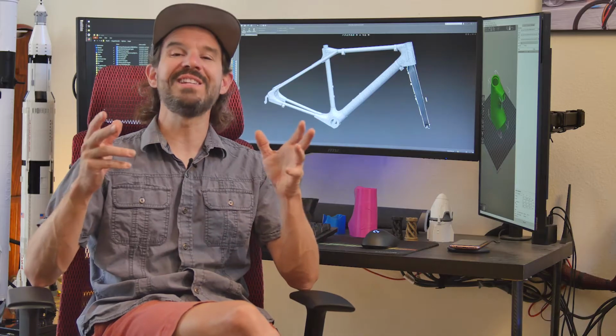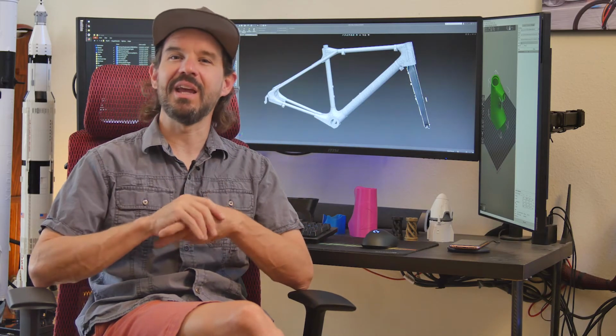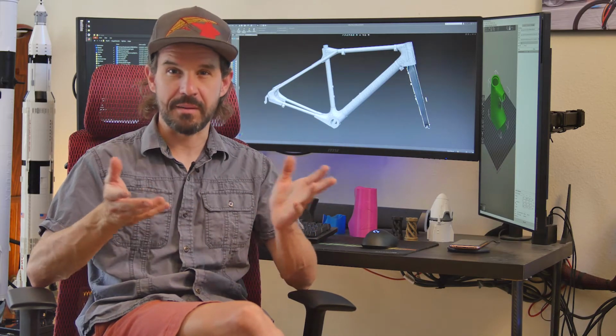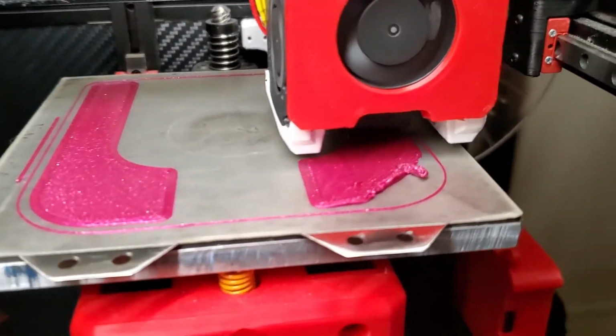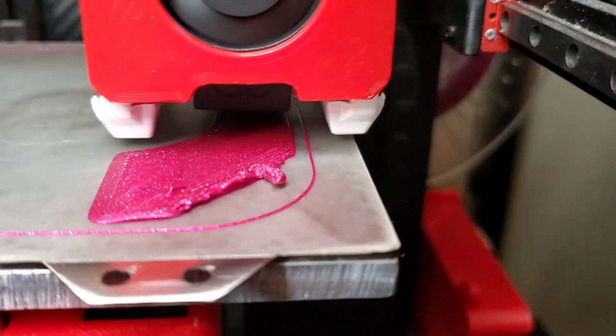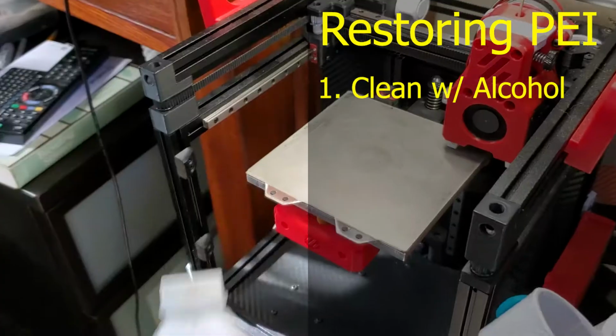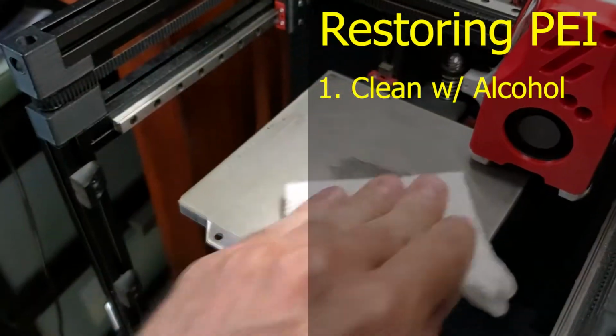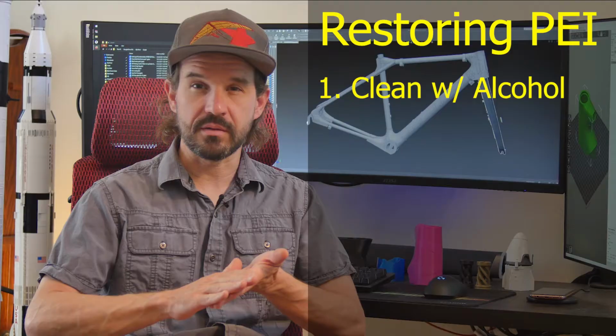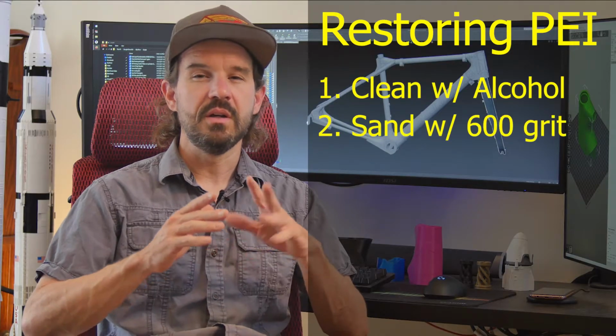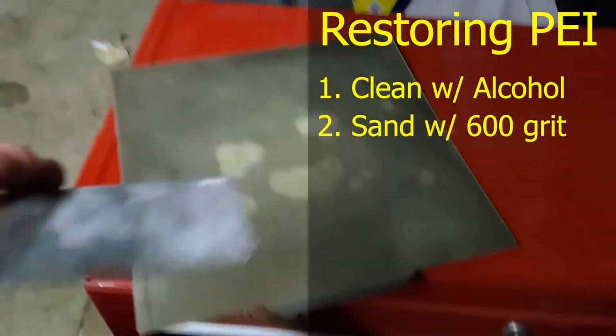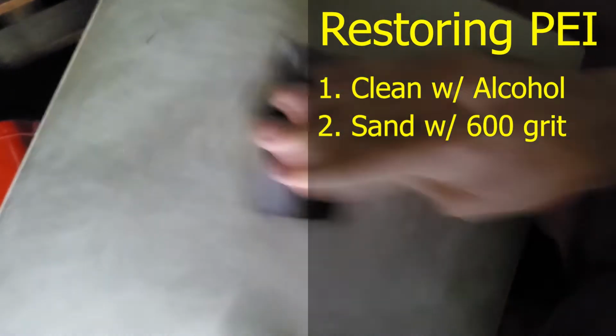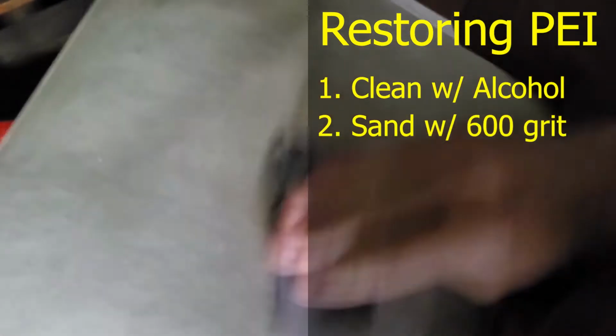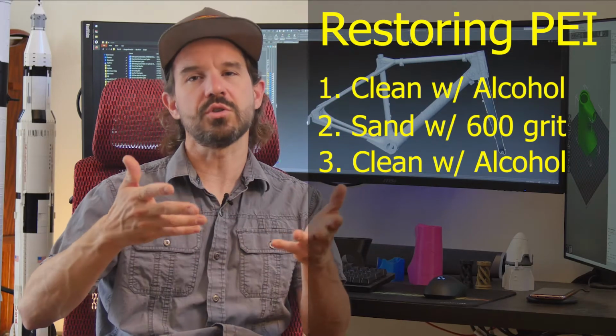PEI works great, but it does have a limit in that it will wear out with time. You'll kind of just notice one day your parts just stop sticking. When that inevitably happens, there are some things you can try. First, clean the PEI sheet with 91% isopropyl rubbing alcohol. If that doesn't quite do it, the next step is to sand or resurface the PEI with a fine grit sandpaper like 600, then clean it with alcohol again, try again.